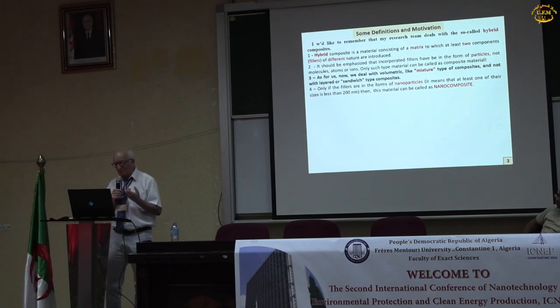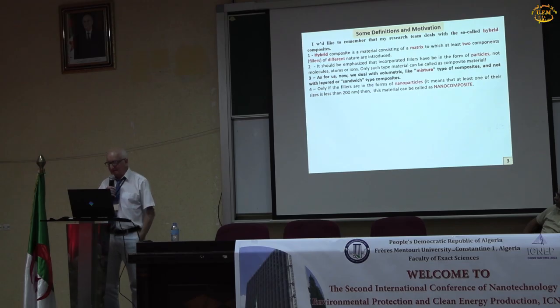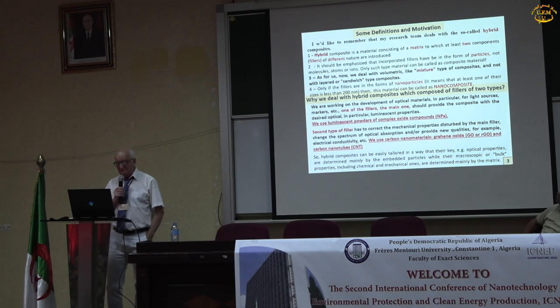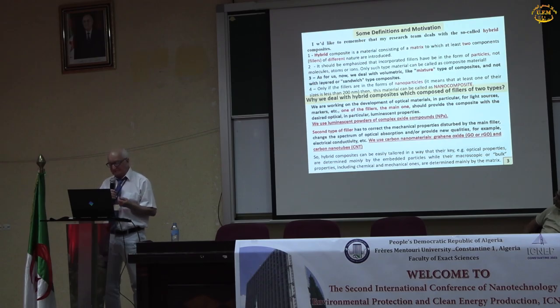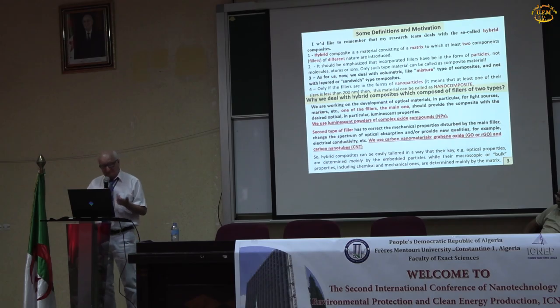Also, only if the fillers are in the form of nanoparticles, meaning at least one of their sizes is less than 200 nanometers, can these materials be called nanocomposites. Why do we deal with hybrid composites, which are composed of fillers of two types? We are working on the development of optical materials, in particular for light sources, markers, etc. One of the fillers, the main one, should provide the composite with the desired optical and luminescent properties. We use luminescent powder of complex oxide compounds. The second type of filler has to correct the mechanical properties disturbed by the main filler, change the spectrum of optical absorption, and/or provide new qualities, for example, electrical conductivity. We use carbon nanomaterials: graphene oxide, reduced graphene oxide, and carbon nanotubes.